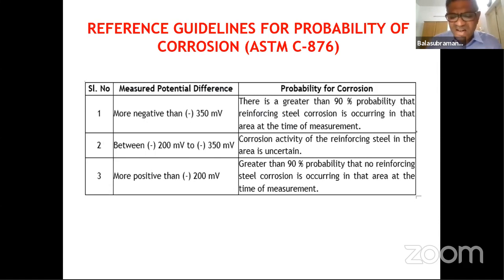For me, this test is again not very useful, because most of the structures we go to are terribly corroded. There is no point in doing a half cell potential test on corroded areas, because obviously the steel has already corroded, the concrete has cracked and spoiled, and there is a loss in diameter. Generally we use this test because we go to a site with a very huge structure, whether a marine structure or a bridge structure, and we are asked to give the rehabilitation methodology as well as a bill of quantity. When you want to calculate the bill of quantity, we need to be very sure, given the limited testing we do. So at that time we do the half cell potential test on the good locations to check whether the visually good locations are in reality really good.